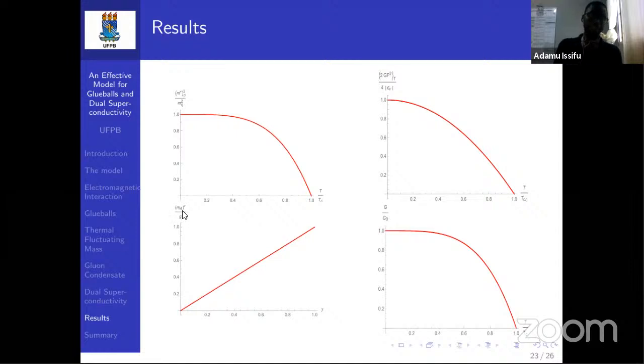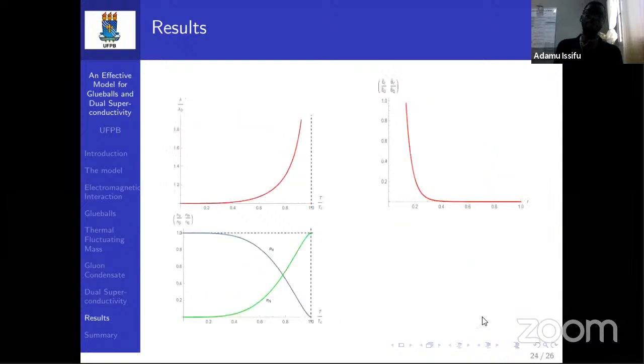Then this is the Debye mass, the Debye-like mass we calculated. So as a function of temperature, it increases with temperature. And then we have the glueball potential as a function of temperature. It also decreases. The glueball decreases as we increase the temperature of the system.